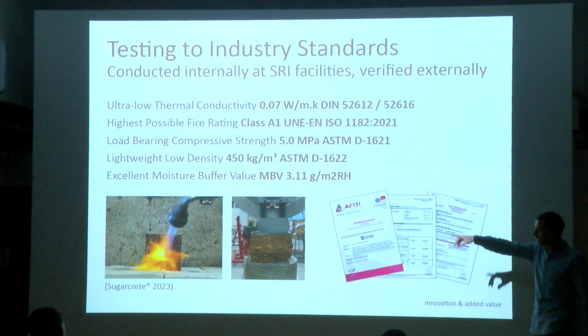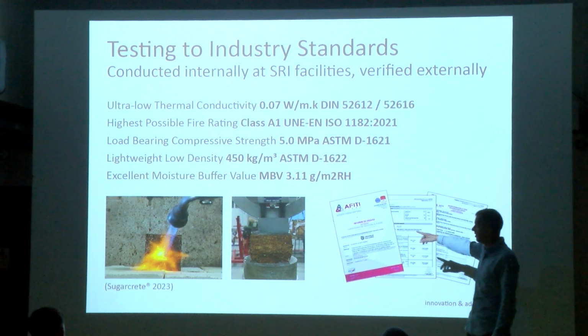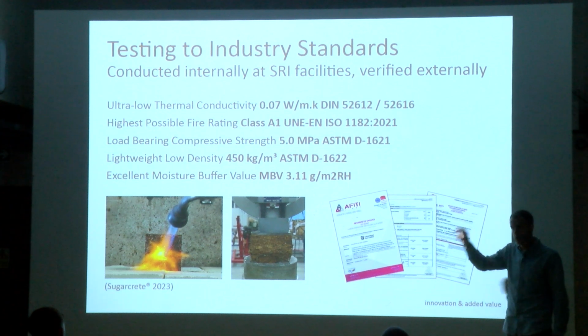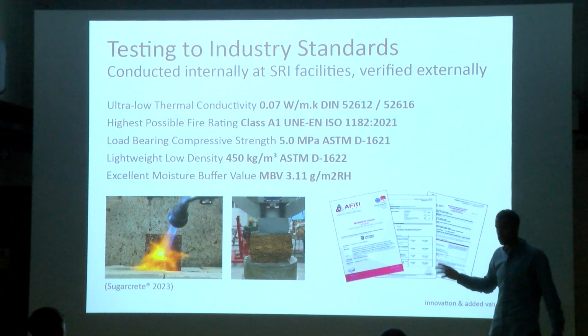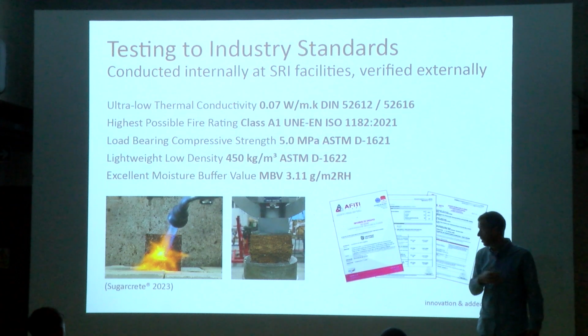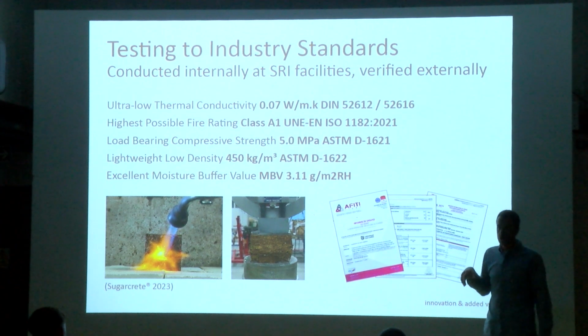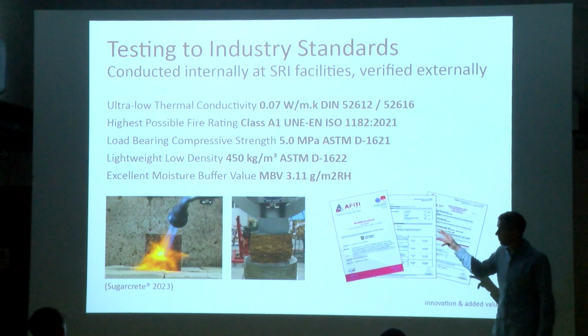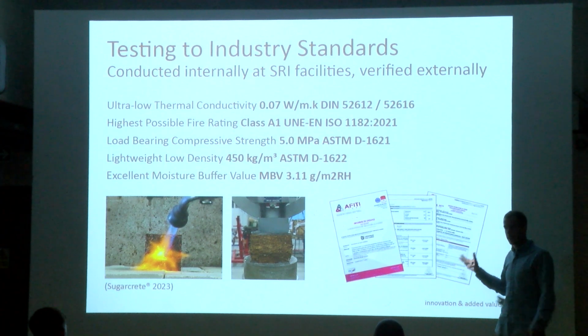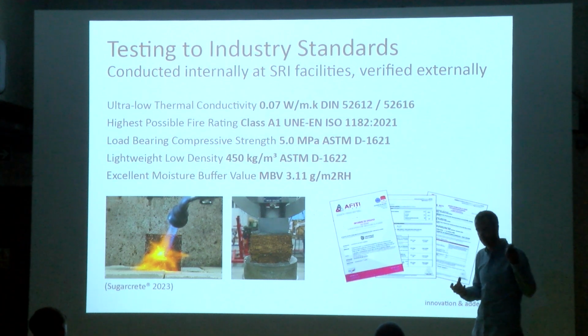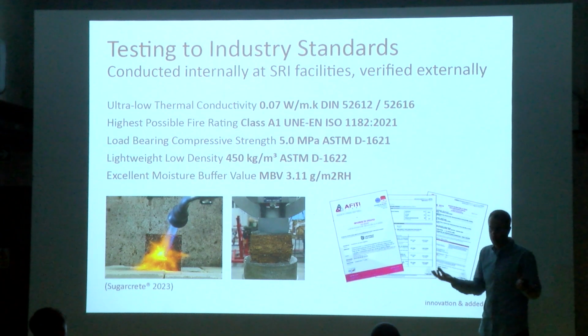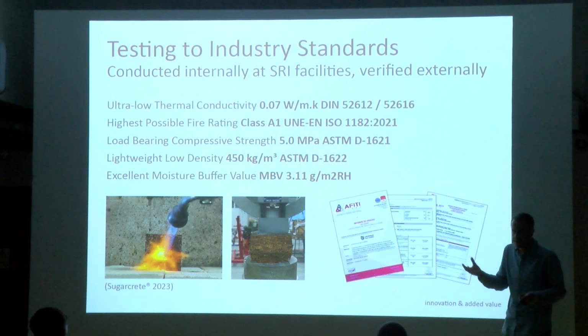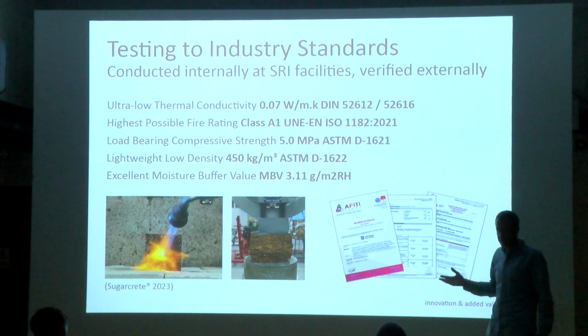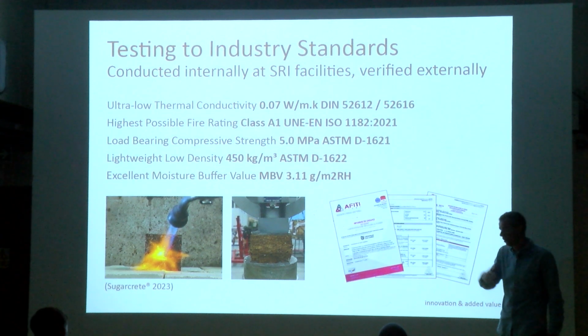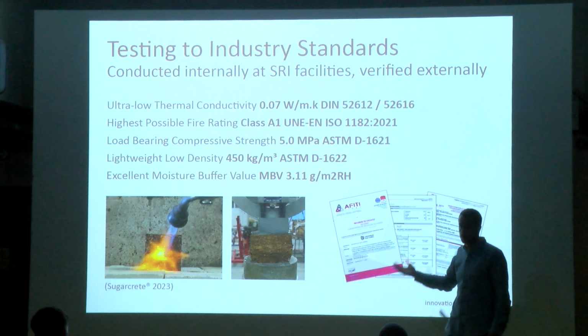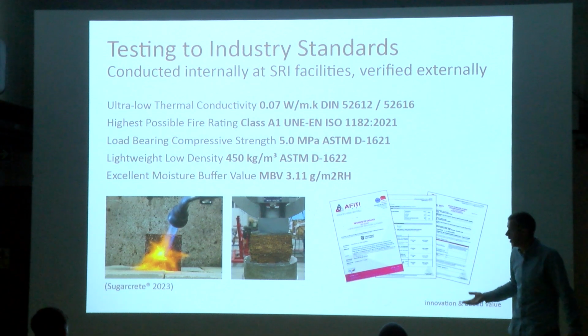As I mentioned, some of these testing are done internally, but then they are all verified externally. So we are working with institutes in different regions of Europe. I was mentioning as an anecdote, we tried to work with the BRE in the UK to have our sample tested there, and they didn't understand that it was one material. They wanted to test the bagasse and the binders independently, which wouldn't make any sense because we know that bagasse ignites, so the test will fail immediately, but they wouldn't accept that this material was a composite material. We had to go to an external laboratory in Europe that was used to work with biomaterials, and we were able to do it there.